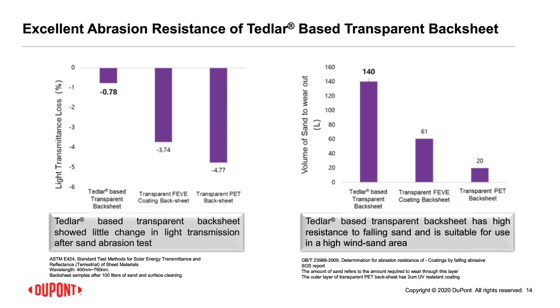And on the left, what we are doing is comparing the Tedlar-based transparent backsheet to two other competitive backsheets. This is a standard test for solar energy transmittance. After the completion of the test, as you can see here, after 100 liters of sand abrasion and surface cleaning, the Tedlar-based backsheet only loses about 0.78% of the total light transmittance, while the others are much